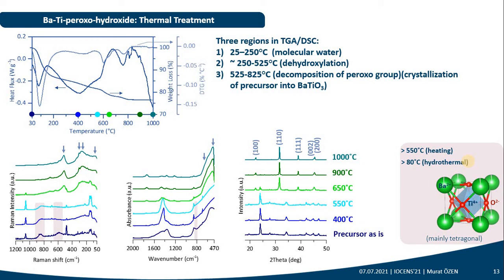we have three main regions: at about 25 to 250 degrees Celsius, which is the evaporation of molecular water; 250 to 525 degrees Celsius, which is the dehydroxylation of hydroxyl groups; and 525 to 825 degrees Celsius, which is the decomposition of peroxo groups and the crystallization of the precursor material into barium titanate.